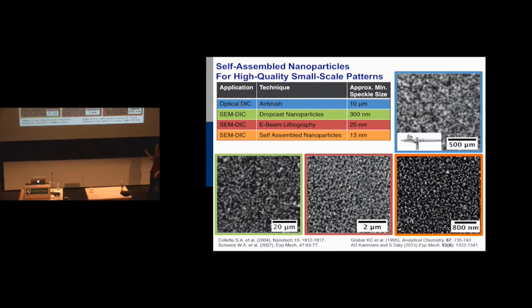And so what we did was we created a silanization procedure. This is not cherry-picked. We created a way that we can chemically functionalize our specimen. We take the specimen, we dip it in a batch of chemicals. What ends up happening is that you get pendant functional groups on the surface that coat the entire surface. And then when you drop your nanoparticles in, each little group grabs one nanoparticle, and you have this beautifully uniform spread of nanoparticles on the surface that we can track. And when we're done, we can just chemically break the bonds and get rid of them for EBSD.